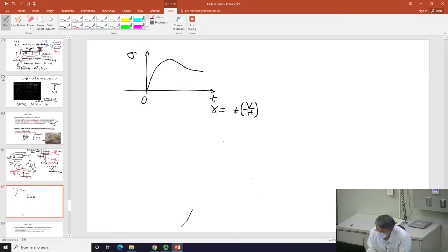I hope I didn't go further than what you know. Then there's this yield point, and the movie shows that you observe shear banding here. I just want to assure you that for large enough shear, this point goes with the shear rate to the minus 2/3 power.